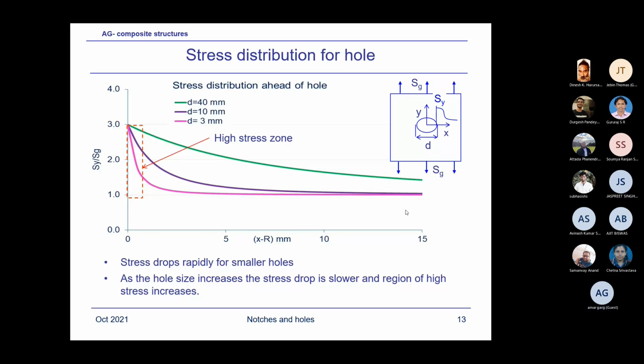Now, what this diagram tells us, when the hole is of a smaller diameter, like 3 millimeters, say, this is 10 millimeter and this is 40 millimeter. And what you are seeing, the stress distribution ahead of the hole changes depending upon the diameter of the hole. Even though the stress concentration factor, that is sigma_y over sigma_g, this is for quasi-isotropic, that's why here this is terminating at 3, because for a quasi-isotropic, stress concentration factor KT is 3. If it's significantly anisotropic, KT could be 4 or even 5.